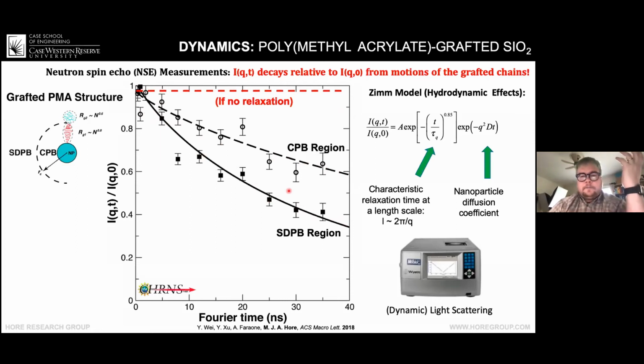Since we're looking at polymers in solvent, one model that we can use for the dynamics is the Zimm model, which incorporates hydrodynamic effects. If you're familiar with this model, this may look a little different than how it's typically presented, but this is how it appears in terms of the intermediate scattering function. Basically, the intermediate scattering function here will decay as this stretched exponential with this exponent here of 0.85. And then this term here takes into account the fact that the nanoparticles are diffusing in solution at the same time. So this tau is the relaxation time we're going to fit for by fitting this function here. And we'll get the nanoparticle diffusion coefficient from DLS. So we can combine everything together here.